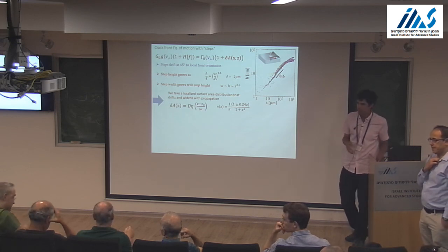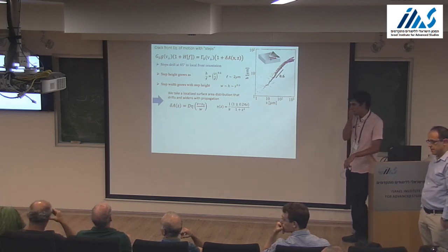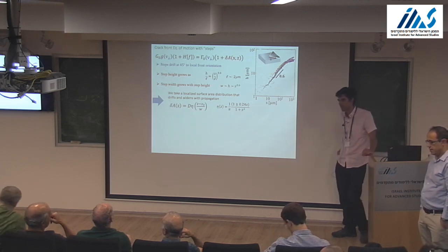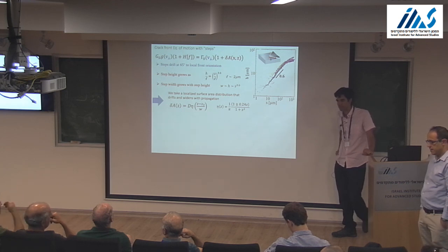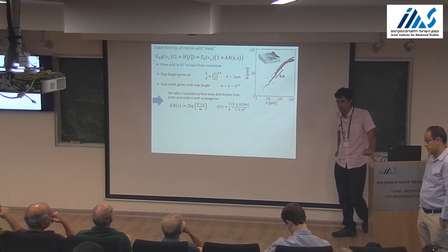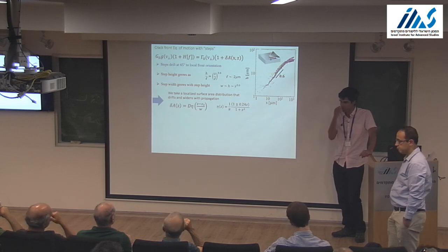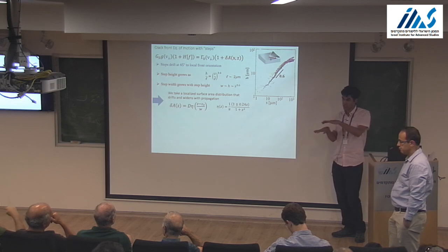So perturbations decay theoretically if the mode 1 loading is perfect, but if there's any mode 3 admixture, then the situation's always unstable. Do you think it's possible that there's just a little bit that's always creeping in? Well, if we had a substantial mode 3 component in our experiments, we would see a preferential polarity of the steps.